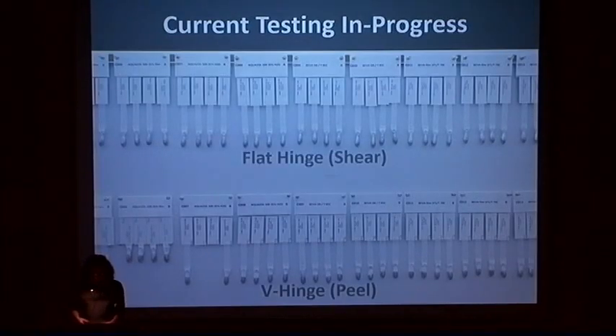We then tested 25 adhesives and tapes applied in a variety of methods. When possible, we applied 2 different carriers, Japanese paper and Holitex, for a total of 50 combinations of adhesives and tapes. The contact area for each is, again, 0.5 square centimeter. Each combination was tested in shearing and peeling tests.